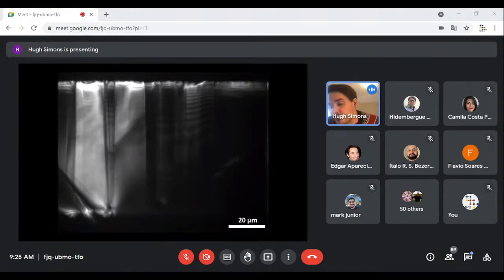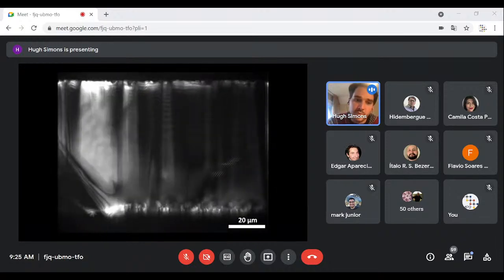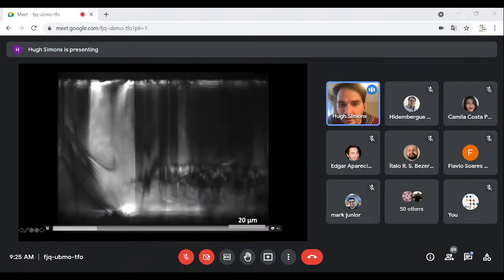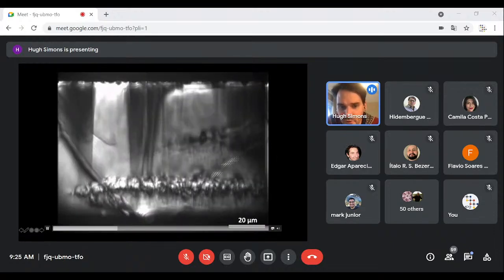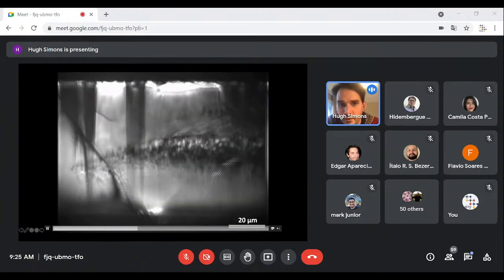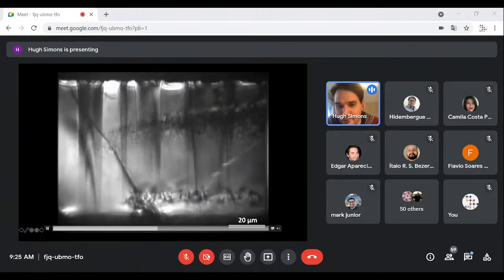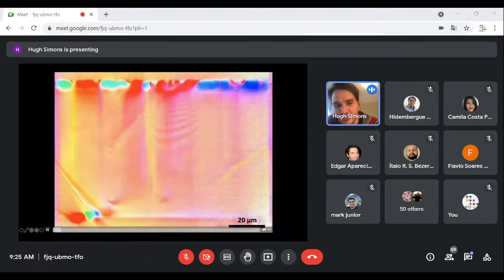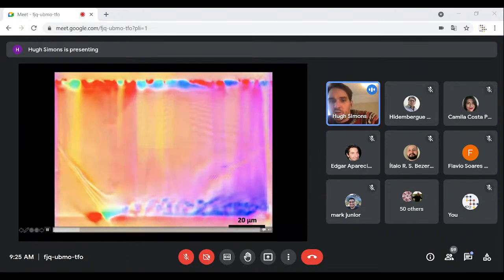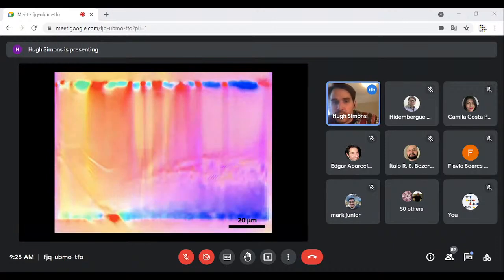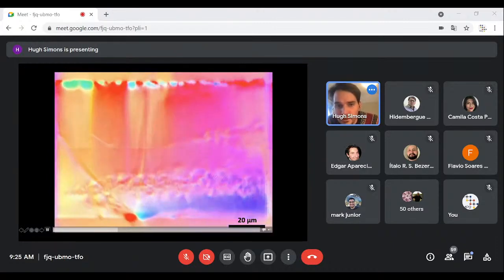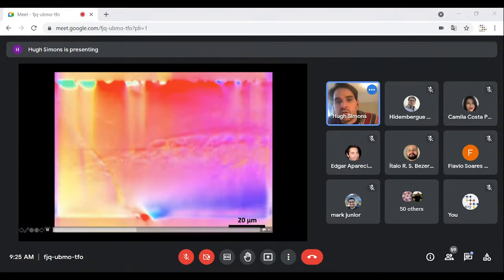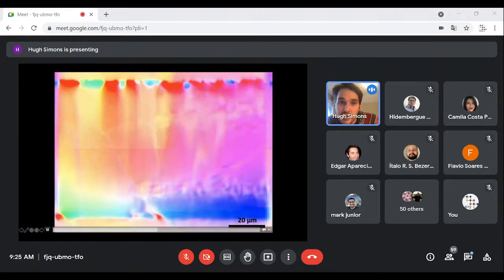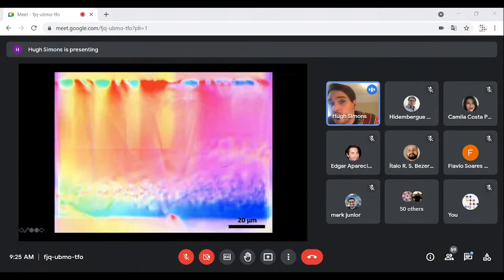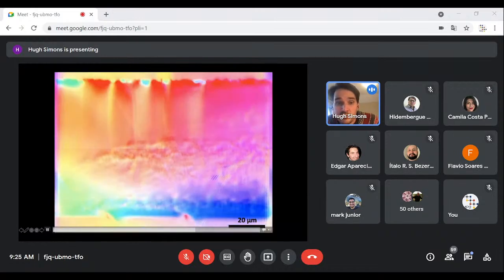We're also able to test different methods of visualizing them. For example, taking slices and moving through the material to visualize how these dislocation bands are distributed through the material, and they create these very dramatic videos of slices essentially moving through the sample. And so here you can see these colorful plots show the lattice misorientation as a result of these dislocation bands. And I think quite clearly here you can also see the deformation in the surface of the material.